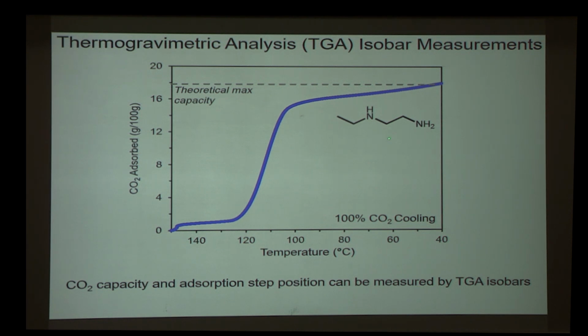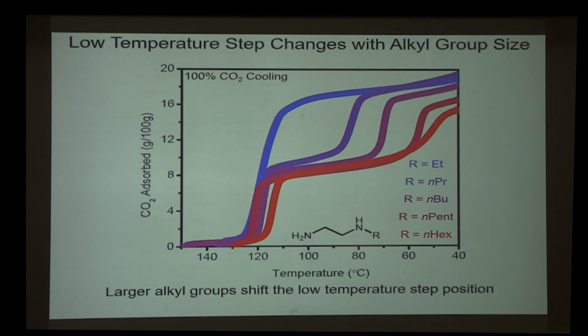And what we found is that when we used the small ethyl group, as expected, there was a single adsorption step. But surprisingly, when we went to any alkyl group larger than ethyl, now we unexpectedly saw 2 adsorption steps. In each case here, we see one step at 120 degrees, accounting for half of the expected capture, and then the remaining expected CO2 capture was accounted for in a subsequent step. And the spacing between these adsorption steps got larger and larger as we increased the size of the alkyl group. This 2-step behavior is undesirable. I mentioned that the advantage of these materials is accessing a massive working capacity in a single sharp adsorption step. And here, we are effectively cutting that capacity in half.